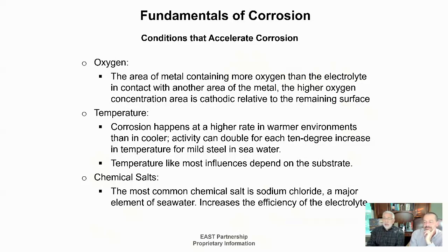Gotcha. Okay, so there are several different conditions that accelerate corrosion, oxygen being one of them, temperature another. Depending where you are, when temperature goes up, the kinetic energy in that material increases, and that movement of atoms and molecules will increase the rate of corrosion. And again, I'm just using seawater as an example, but for each 10-degree increase in temperature in seawater, you can double the corrosion rate. That's crazy. It is crazy. So it's any water that has that balance.